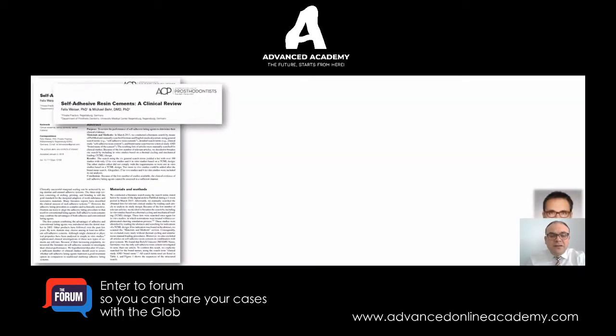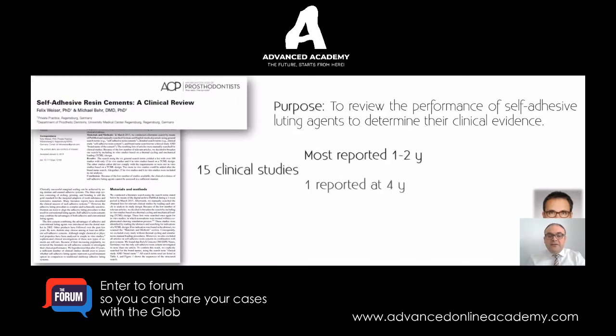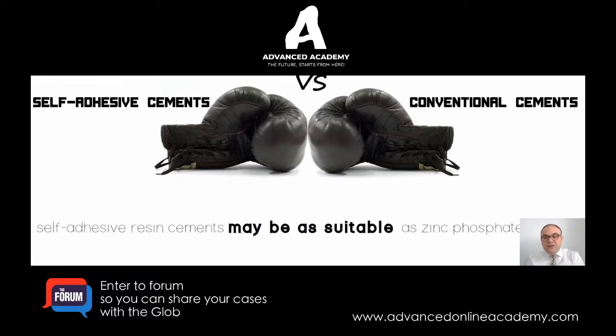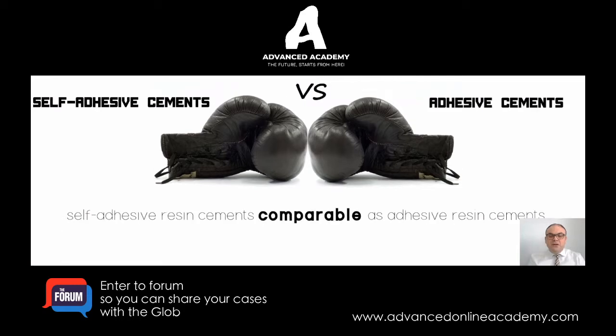So what evidence base do we really have? You can see here, this is a nice clinical review on self-adhesive cements that looked into 15 studies, some of them in vitro studies that involve chewing simulation. When we compared self-adhesives to conventional cement, the self-adhesives can be used as well as the conventional cements. There was a little bit more plaque accumulation around the self-adhesive cements. The self-adhesive cements were also comparable in terms of bonding to the tooth structure, but the marginal adaptation of the adhesive cements was better.